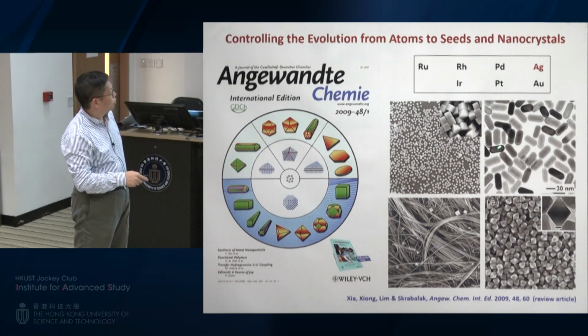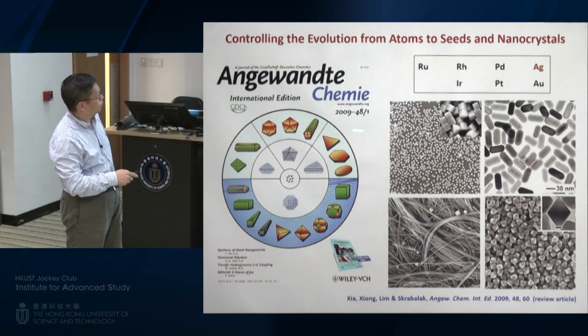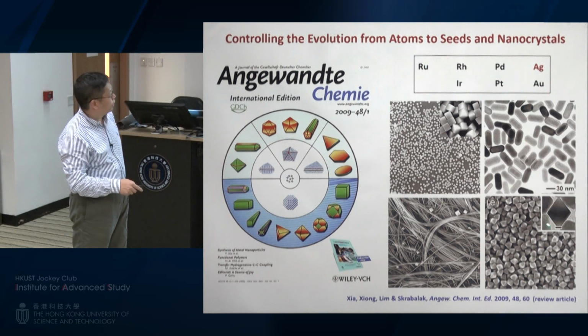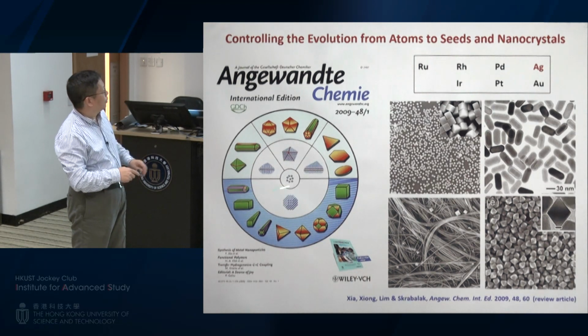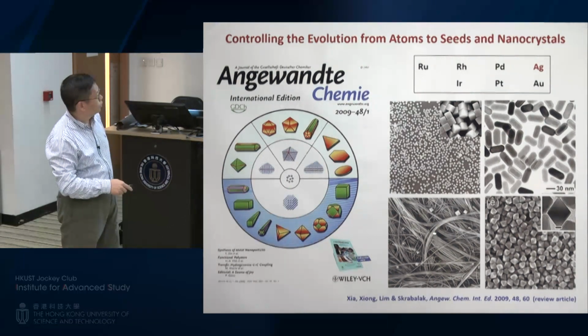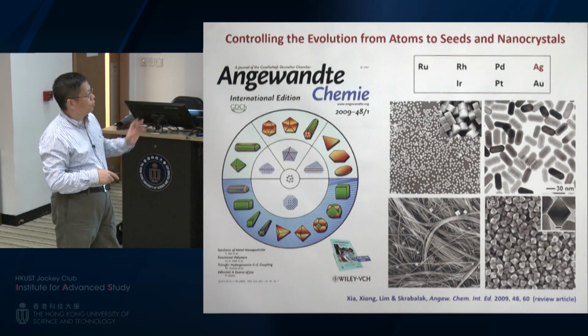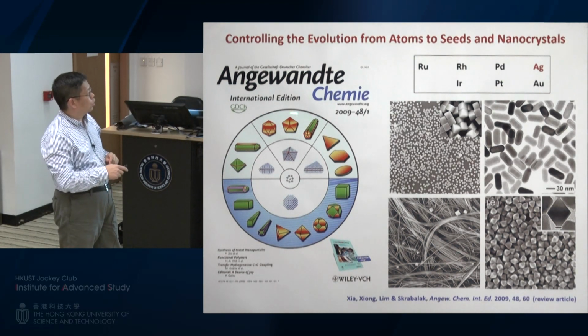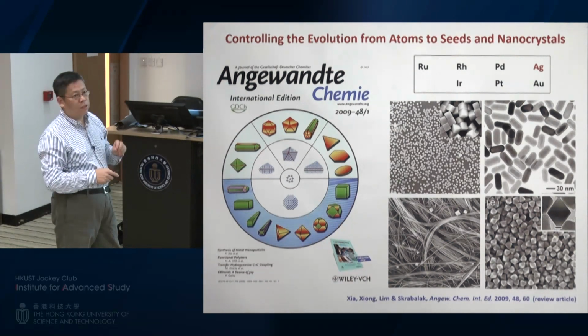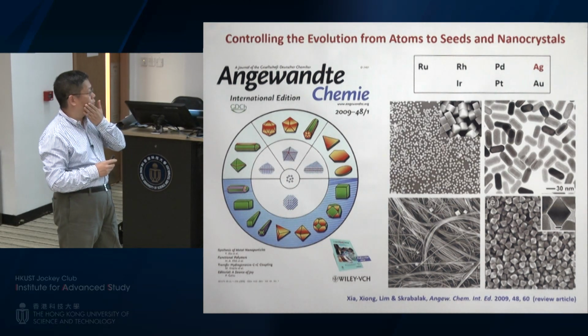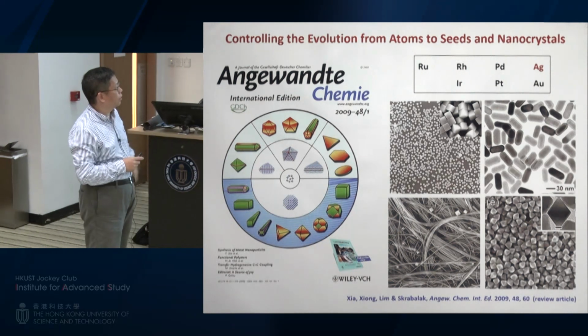And this is the rods sample. It's this one actually. There's some twin defect in it. And this is octahedron. And this is a nanowires actually. It's one of these actually, making them longer where we give you these nanowires. So if you look at the literature now, we can easily make these different shaped nanocrystals with reasonably good purity. Okay, so you can make almost close to 100% purity nowadays.